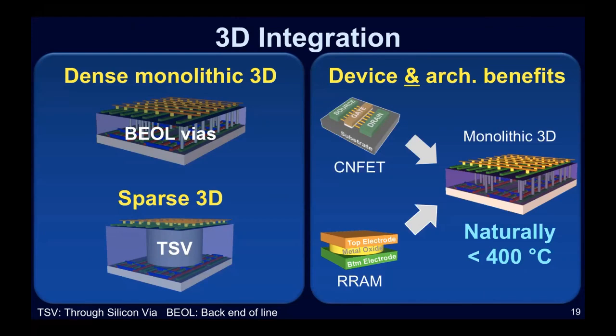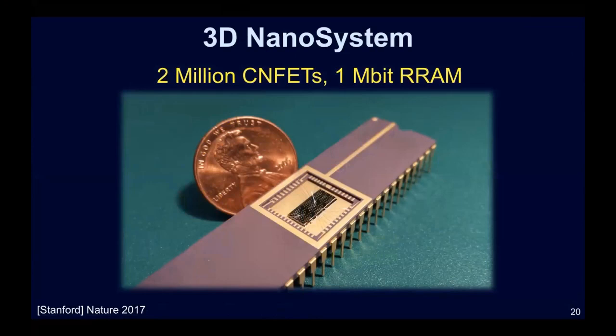How can we put memory and logic on the upper layers of an integrated circuit chip? Using conventional silicon technologies you cannot, because it takes a thousand degrees C to build a silicon transistor, and everything underneath would be severely damaged. This is where carbon nanotubes and resistive RAM come in — both can be built inherently at a very low temperature of less than 400 degrees C. So naturally they enable monolithic three-dimensional integration, which enables a new architecture. In addition to their device-level benefits, CNFETs and resistive RAM give a new architectural benefit that you cannot get with existing silicon technologies.